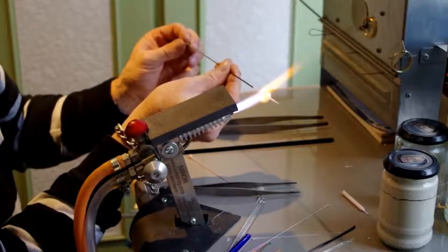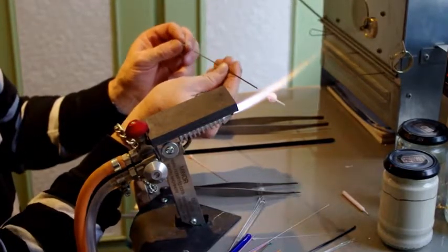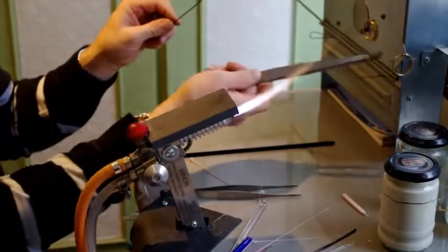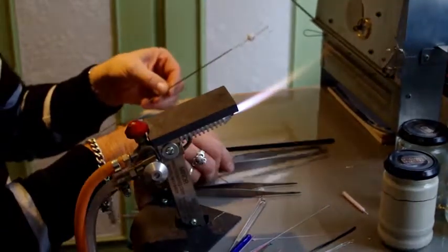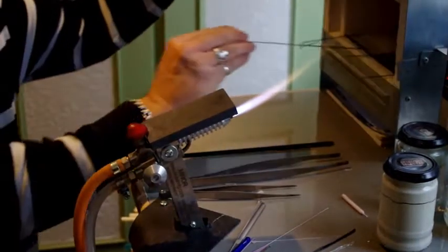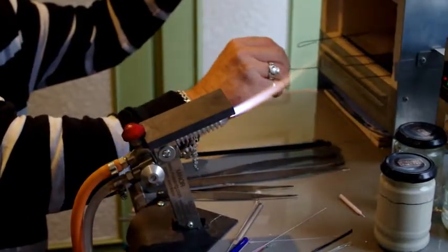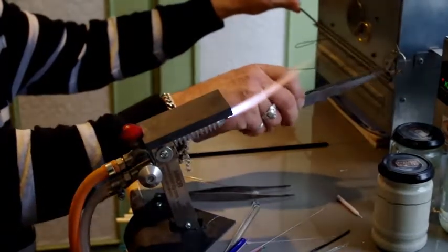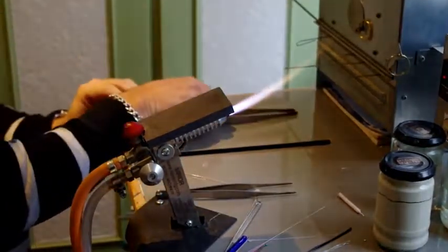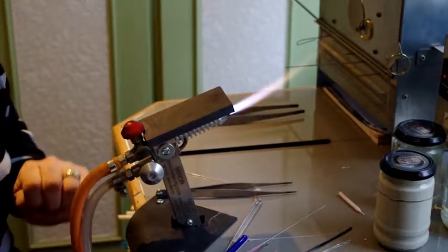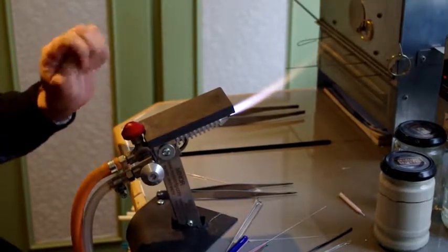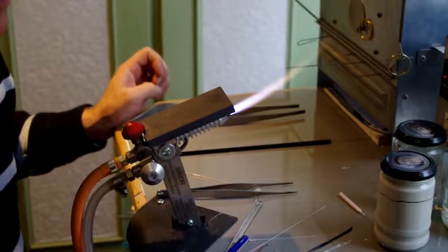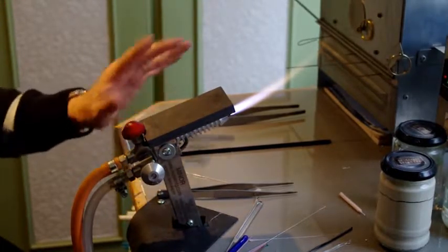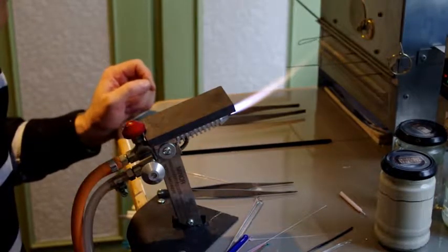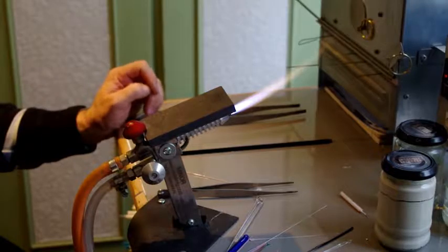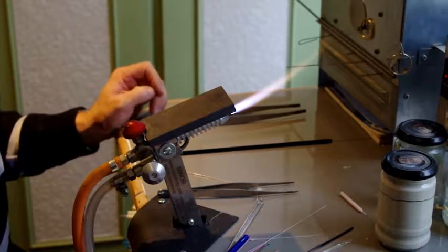Now, when you're happy, that's how you want it. Use the one tweezers, open the kiln and place it into the kiln and put the flap back down. That is on hold at the moment in the kiln at 473 degrees Celsius, hot. When I take it off hold after I've finished doing my working, it will go up to 550 degrees and hold it for 10 minutes so that it all normalises, and then